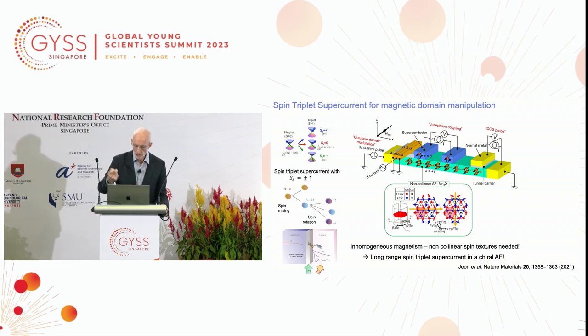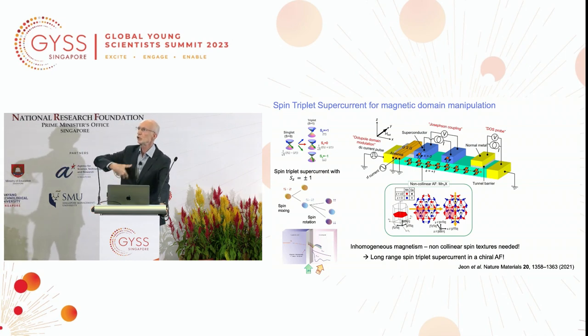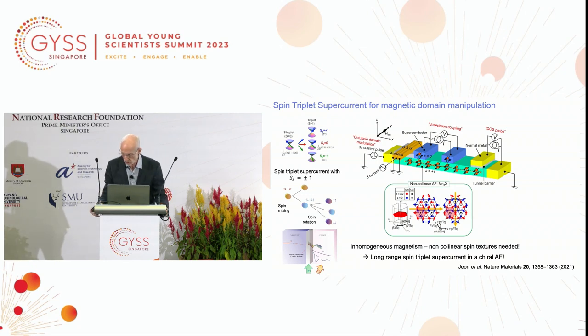Now, it turns out that if we could create that same Cooper pair with the electron spins parallel, in principle, this is called triplet pairing, we could create a supercurrent carrying spin angular momentum. Therefore, we would have a current without any dissipation, which we could use to manipulate magnetization. This has never been demonstrated, but 2 years ago, we demonstrated that by coming back to these non-collinear spin